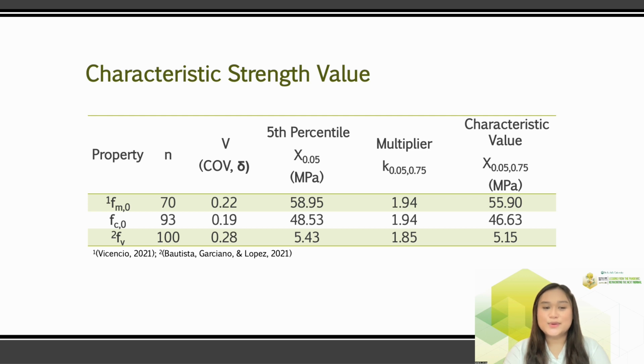Using the ISO 12122-1 standard, the computed characteristic strengths were recorded at 55.90 MPa for bending strength, 46.63 MPa for compressive strength, and 5.15 MPa for shear strength. Since the characteristic strength is computed based on ranking and concentrates on the lower limit or 5th percentile of all the data values, it is expected that the characteristic values are lower than the average mechanical strengths. This table shows the computations for the characteristic strengths where the multiplier is equivalent to 1.94 for the bending and compressive strengths and 1.85 for shear strength, varying based on the number of samples.